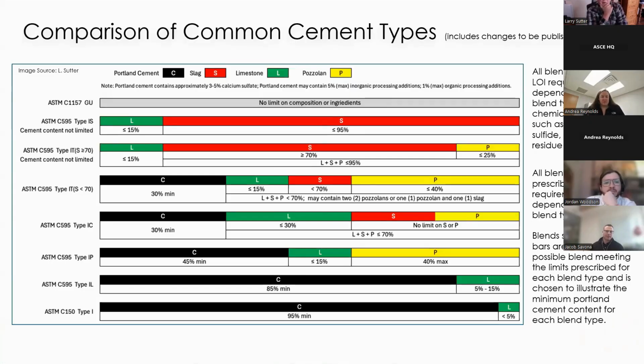And this slide basically summarizes these in terms of, probably most importantly, the clinker content. The black bar indicates the cement content. So moving up from the bottom, your typical C150 Type I cement, 95% cement. And it'll move up a IL, 85% cement, an IP, now 45% minimum. And then the ICs and the ITs. And the ITs in particular, I want to draw your attention to. The IT cements, I think, are the low-hanging fruit. That's where we can really start doing things today with the materials that we're using today, in proportions that we're used to using today. There's really nothing new here. We're just using them in different combinations. And we can get down to 30% cement if we want to with these types of blends.